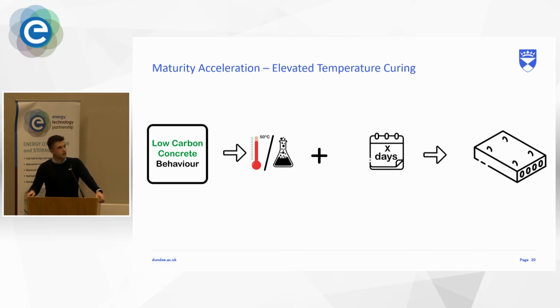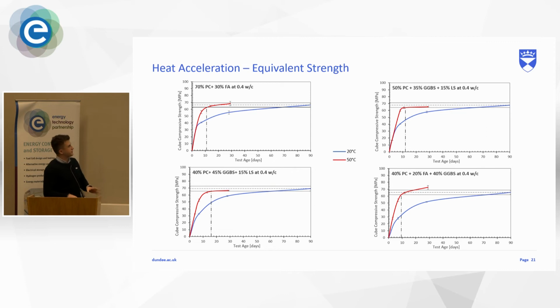So what we know is that the performance and durability are somehow interconnected through the mechanical properties of concrete. So there is a good chance that if we manage to match the performance, the strength, by curing at 50 degrees, the durability will still be unchanged relative to that of the 90-day standard cured samples. And it will become clearer once I explain these graphs a little bit more.